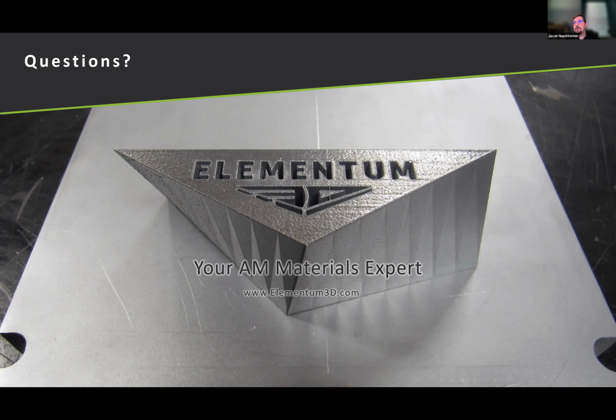So we've done things like control the oxide and therefore get higher thermal conductivities from doing double pass, but it slows your build speed down quite a bit. So I think there's pluses and minuses there. If you have an application that needs much higher thermal conductivity, doing a double pass can help. But if you need good thermal conductivity and build speed, then it's kind of a balance there.